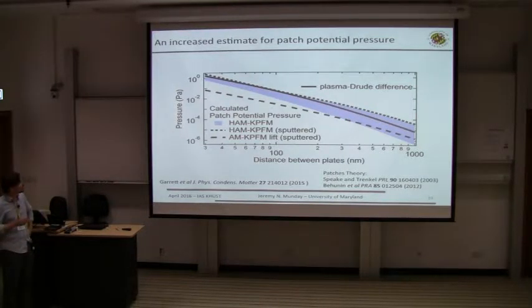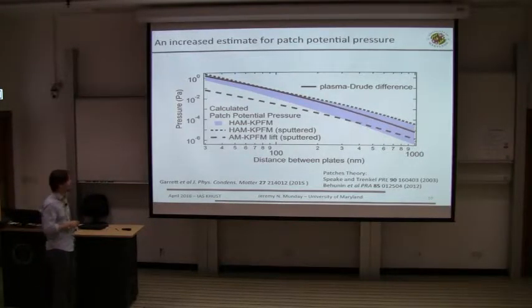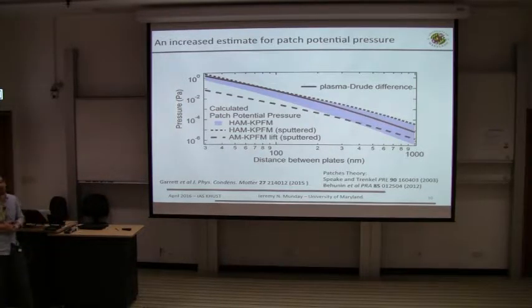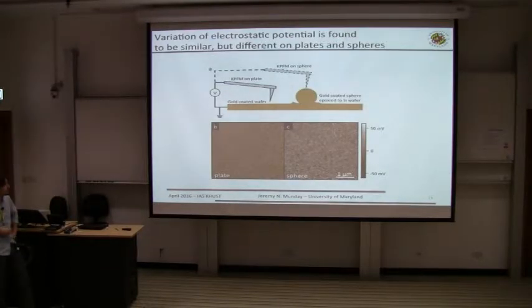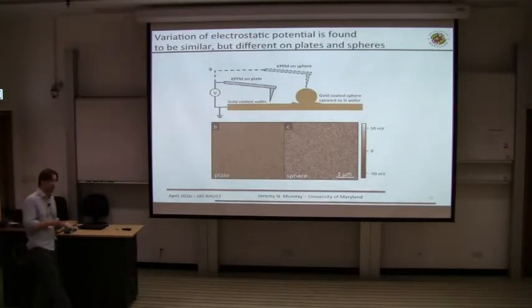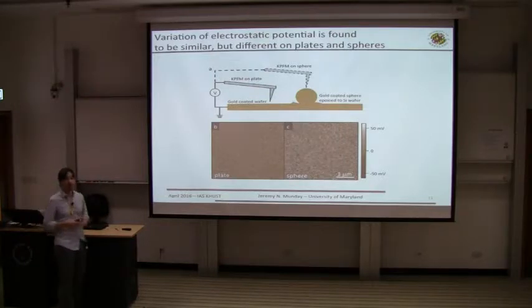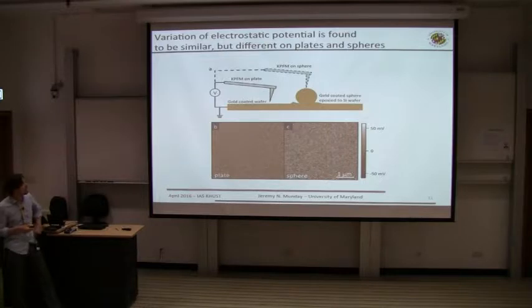And so then also we have, for comparison, the results that we got on the sputtered ones, which are what I showed you earlier, using either the amplitude modulated or the heterodyne potential. So for our sample, we found a lot of variation, so it's really important for us to understand those whenever we make measurements. So those were all on wafers, so on the plane, but obviously you have an experiment, you have a sphere and a plate. So we wanted to see how they differed on these different materials.